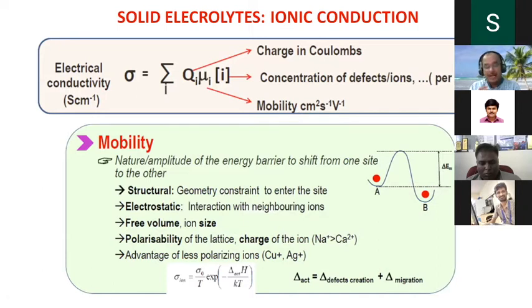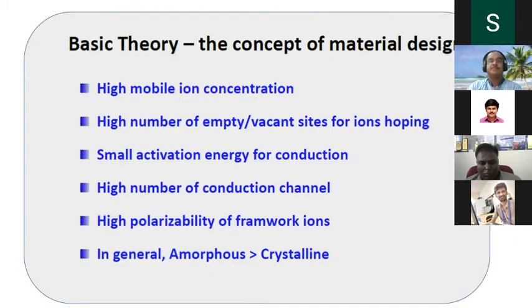So activation energy means how much energy you require for defect creation plus the migration. That's what people used to calculate the activation energy required for these conductions. Which means that the concept of material design should be: high mobile ion concentration, high number of empty or vacant sites for ion hopping, small activation energy for conduction, high number of conduction channels, and high polarizability of the framework of ions.